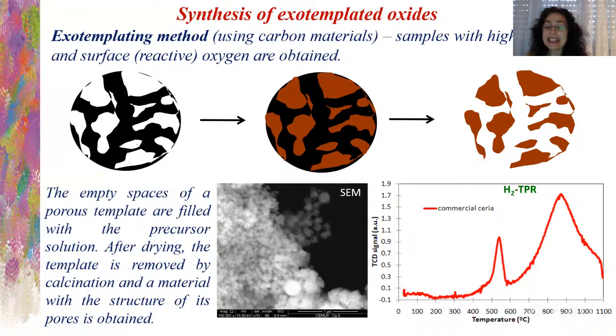So what happens here? We have a hydrogen TPR, which is temperature programmed reduction in hydrogen. So it reduces the oxygen species, shall we say, and then we see here two peaks in the TPR. So this first peak is for surface oxygen reduction, and the larger peak at higher temperatures is for bulk oxygen reduction. And these are the results for the commercial ceria sample, okay?